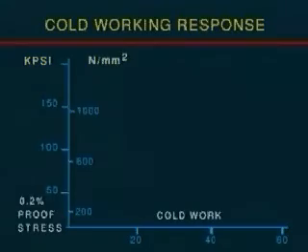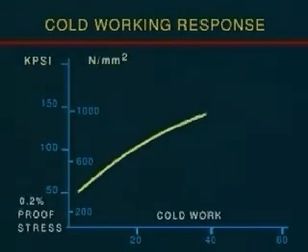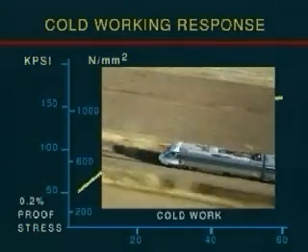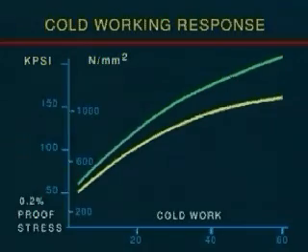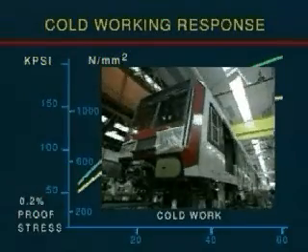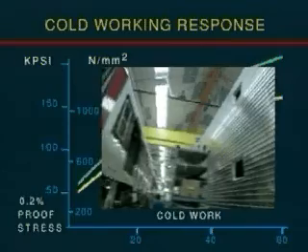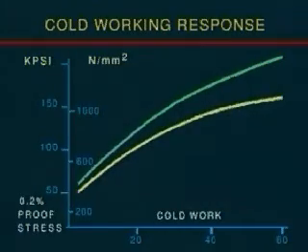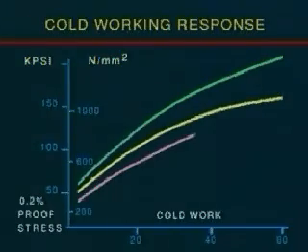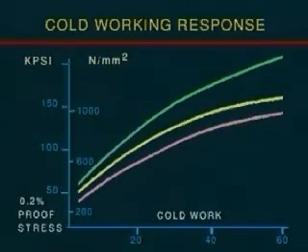It's possible to increase the strength of this steel by cold working it, and this stronger version is used to design lighter, longer-lasting things, such as this high-speed train. The response to cold working can be increased by altering the chromium and nickel content, and this type of higher strength steel was used for Eurotunnel vehicle wagons to obtain a more cost-effective, lighter design. Alternatively, the composition can be adjusted to reduce the cold working response, allowing components to be made easier and cheaper.